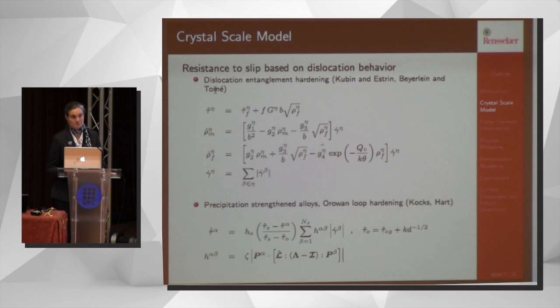Now, once those dislocations are trapped, they become forest dislocations, so those two minus terms in the mobile dislocation density evolution come into the forest dislocation density as source terms. And then for the forest dislocations, we have a thermal recovery term that allows these dislocations also to go away more quickly as the temperature goes up.